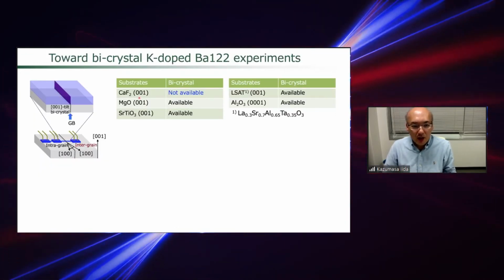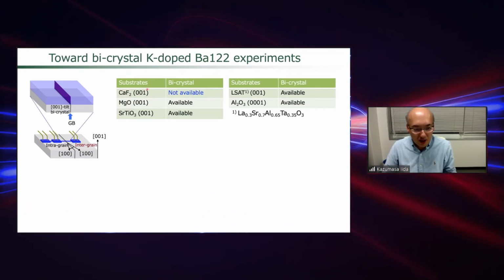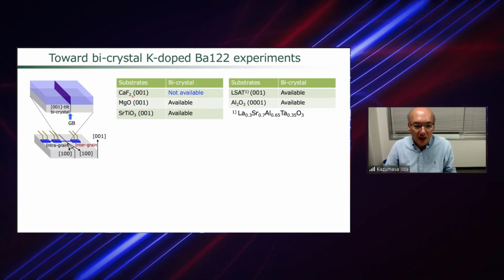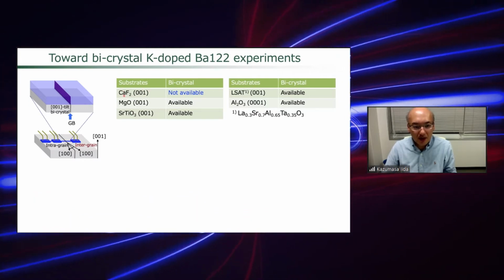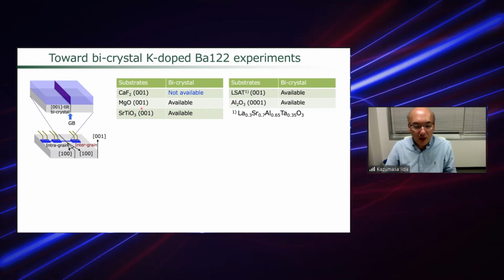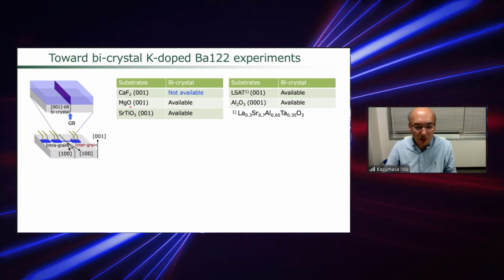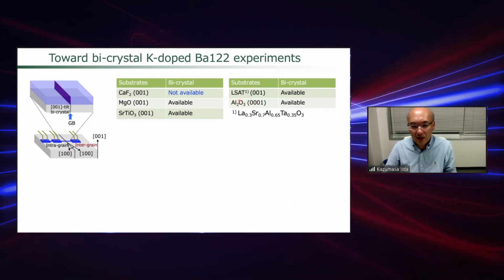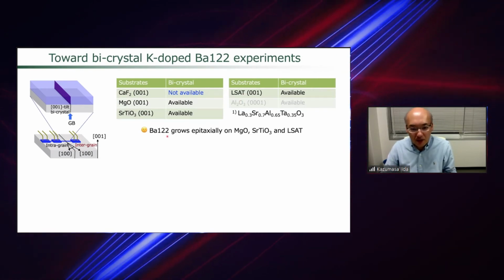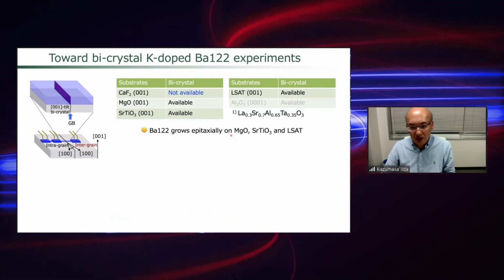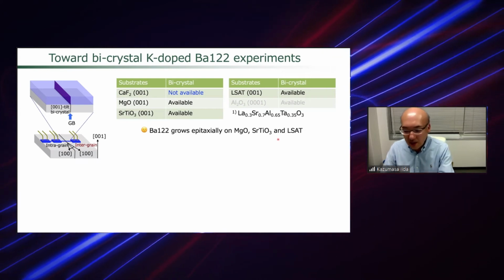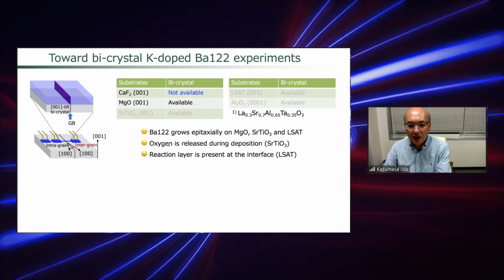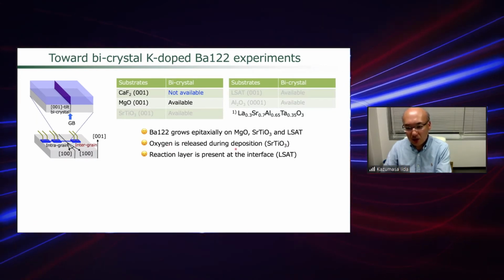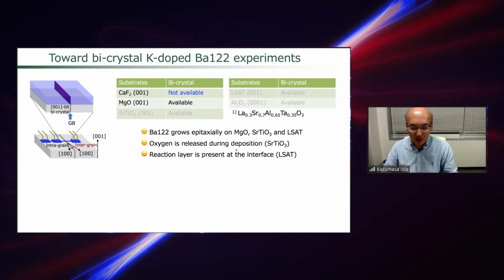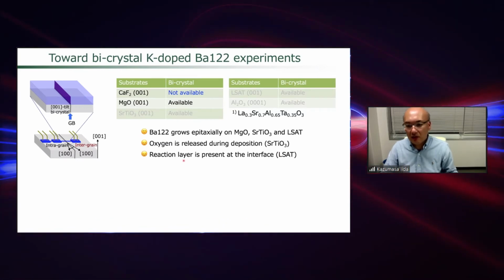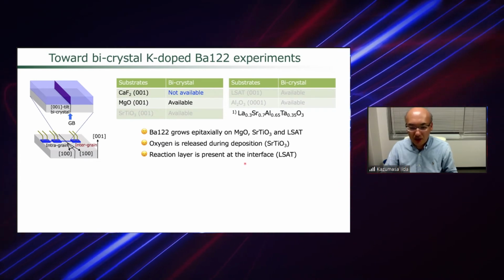But as mentioned before, we have successfully fabricated epitaxial thin films on calcium fluoride. Unfortunately, as far as I know, bicrystal calcium fluoride substrates are not commercially available. Only oxide bicrystal substrates, such as magnesium oxide, strontium titanate, sapphire, and YSZ, are available. But barium 122 and cobalt-doped barium 122 grow epitaxially on those substrates, which is good. But for strontium titanate, the oxygen is usually reduced during the deposition, especially under ultra-high vacuum conditions. For the LSAT substrate, a reaction layer is always present at the interface between the barium 122 and the substrate.